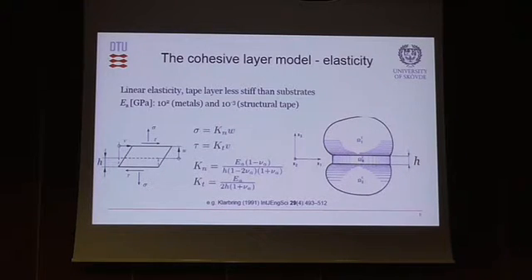Let's start with the model. From linear elasticity, we can do asymptotic analysis, and this has been done a lot. What it boils down to, when you consider that the metals are much, much stiffer than the adhesive, or in this case, the tape, is that it's two deformation modes that dominate completely. That is the peel deformation, where you separate, and the shear deformation. Those two dominate, and you have stiffnesses that are dependent on the adhesive in this way. If you separate and everything around is much stiffer, you get uniaxial strain, not uniaxial stress. You get much higher stiffness.